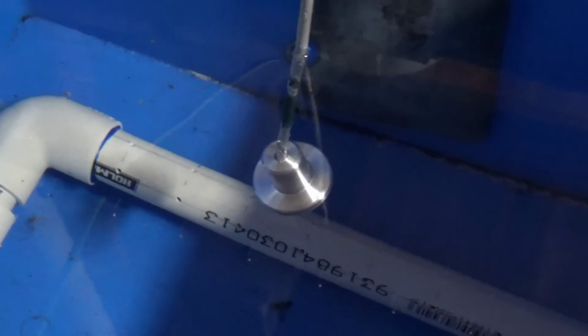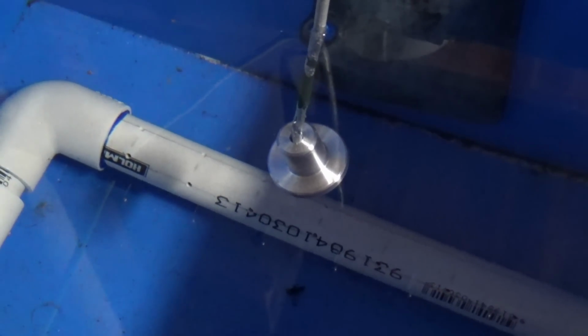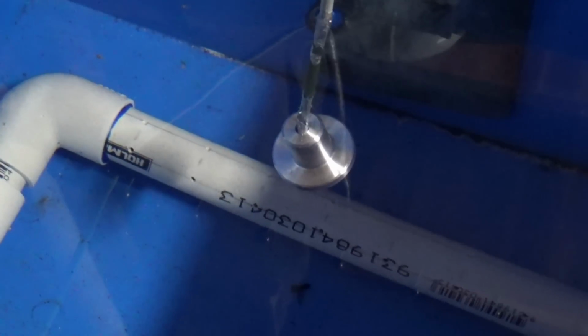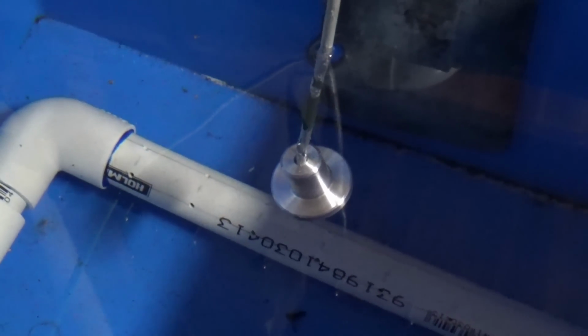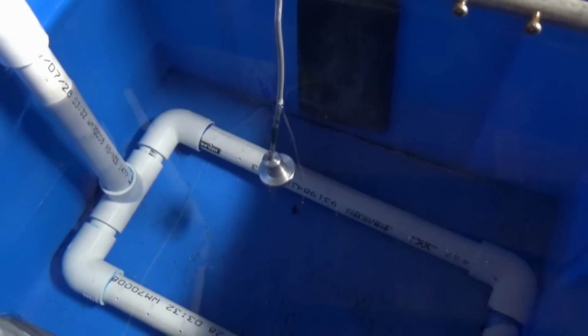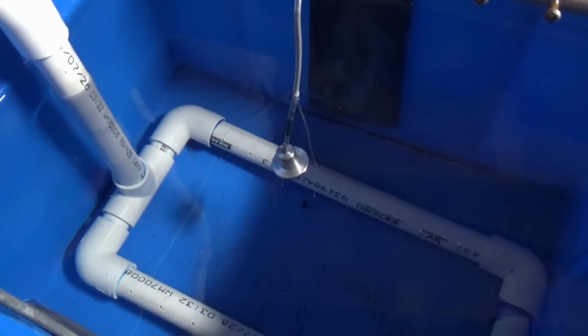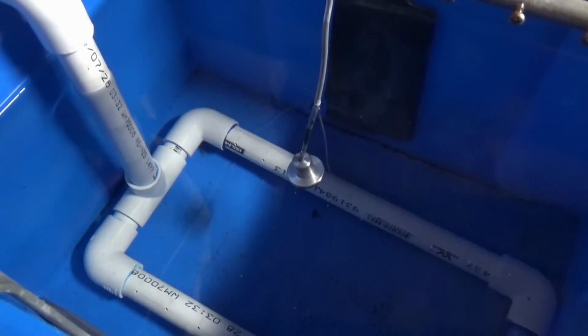Okay, we'll give that maybe an hour and a half, 2 hours at 15 volts. I've set the power supply to 0.4 of an amp, but it's only taking about 0.12 at this stage. Okay, that's been in for about 2 hours, so I'll take this out, give it a really good rinse, and then it's straight into the dye.